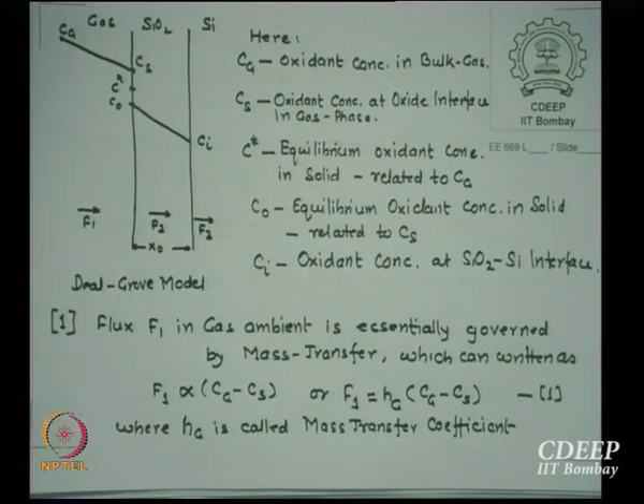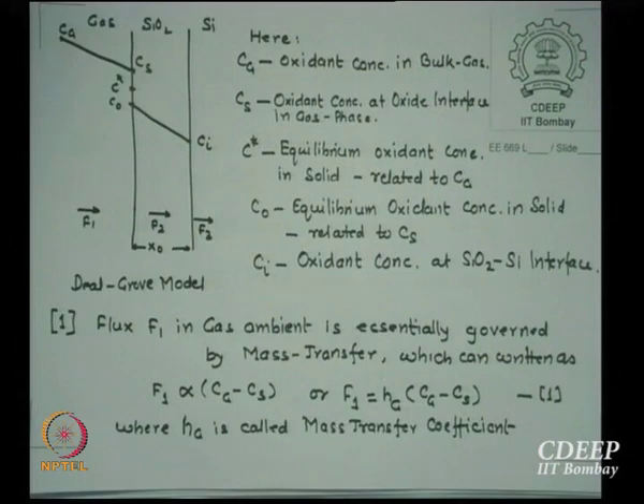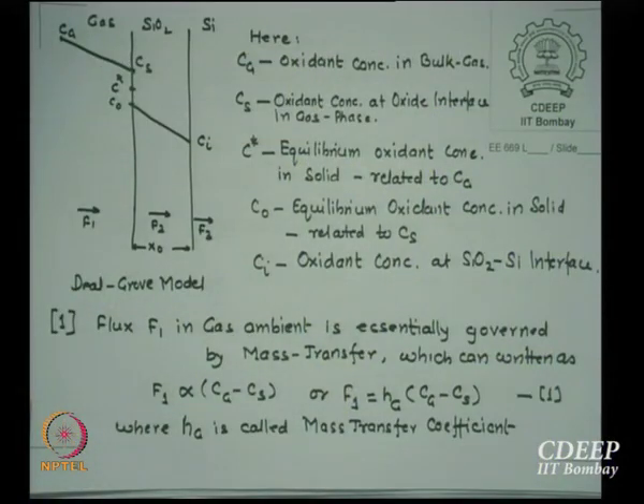However, there are terms which you should learn from thermodynamics, called total pressure and partial pressures. Partial pressure is defined as the pressure of a gas inside a stream at a given temperature in a given area. So if I know F1 is hg times this, I want to replace Cg and Cs, which are not known to me. Cg and Cs cannot be monitored. So I will try to find equivalents in terms of partial pressures. And if I know the partial pressures, then using Henry's equation, we will find out the solid phase concentration for these partial pressures. So at the end, I am interested to correlate Cg, Cs with C star and C0. This is what I am looking for.